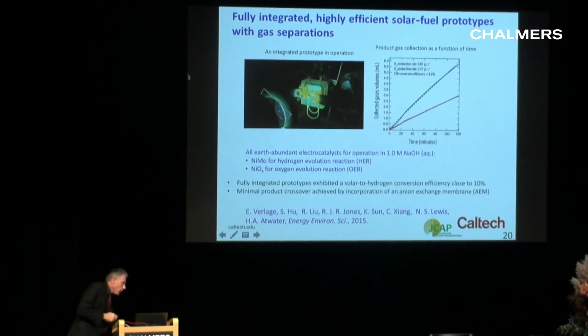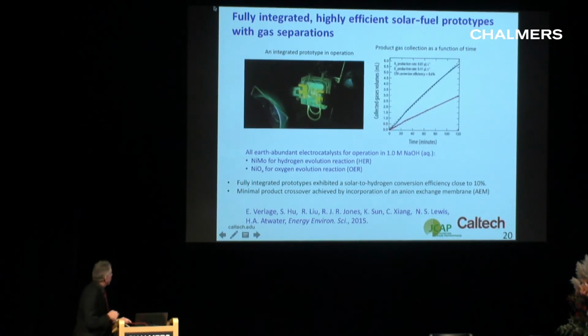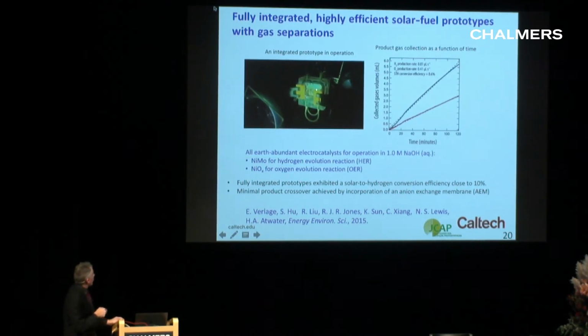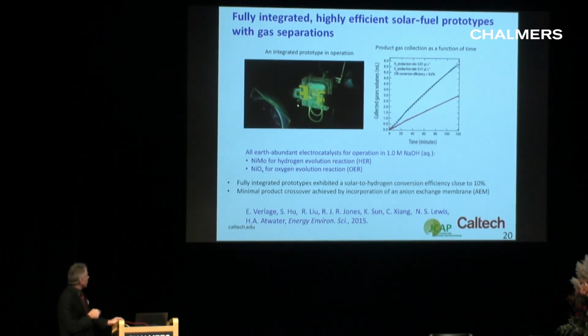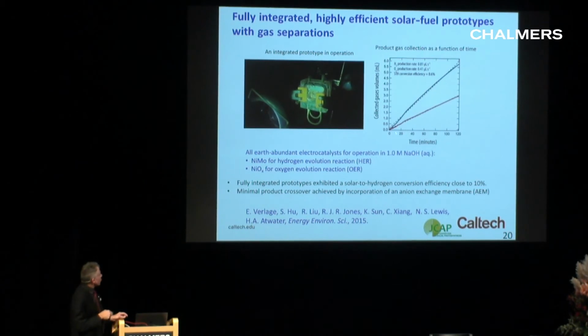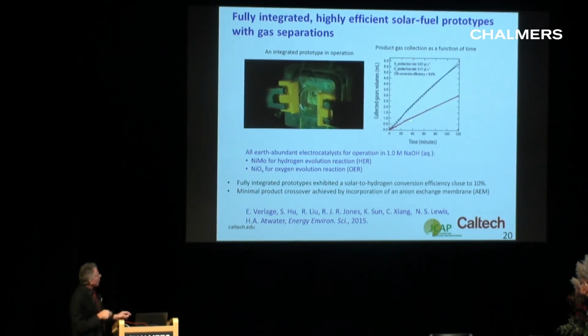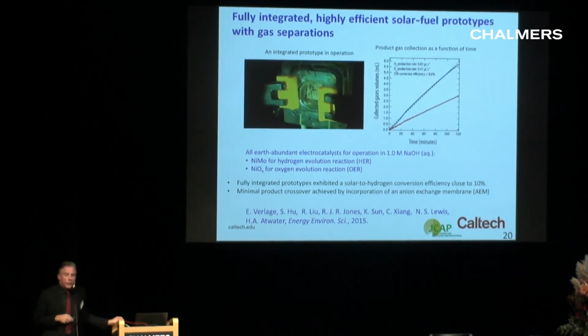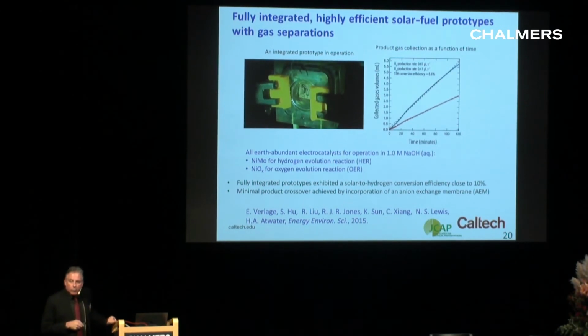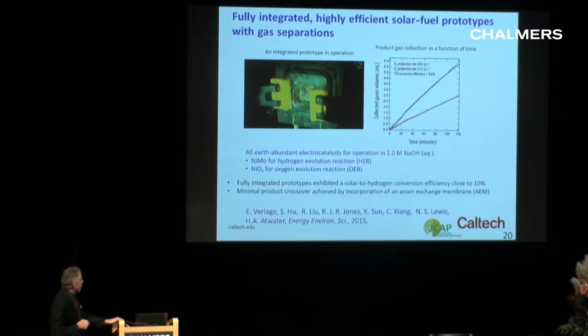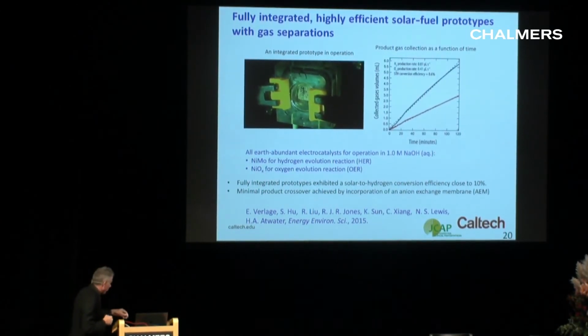You can see here, if we look closely, you can see bubbles effervescing here. That's the indication here we're making, on the anode side, oxygen, and on the other side, hydrogen. If you collect the gas, it comes out in a 2-to-1 ratio, which is exactly what it should be, since our reactant source is H2O.